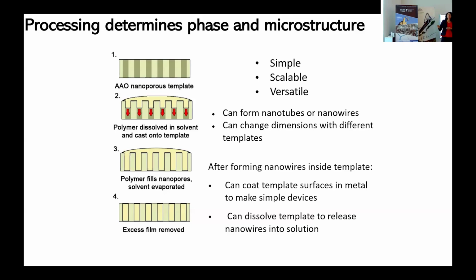So you start with a nanoporous template. These are actually commercially available anodized aluminum oxide membranes, which are used for filtration. So they have sort of nano-sized pores. What we do is we either dissolve the polymer, or we melt it, and then we force it through the porous template. This could just be by capillary action, or by adding some sort of pressure.